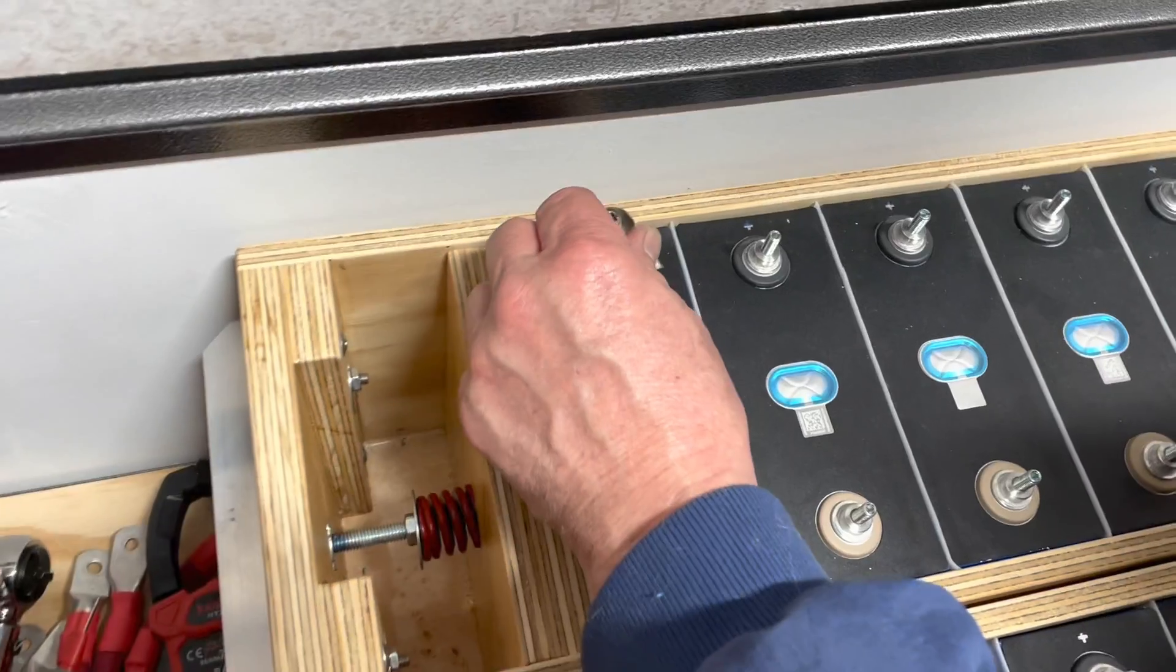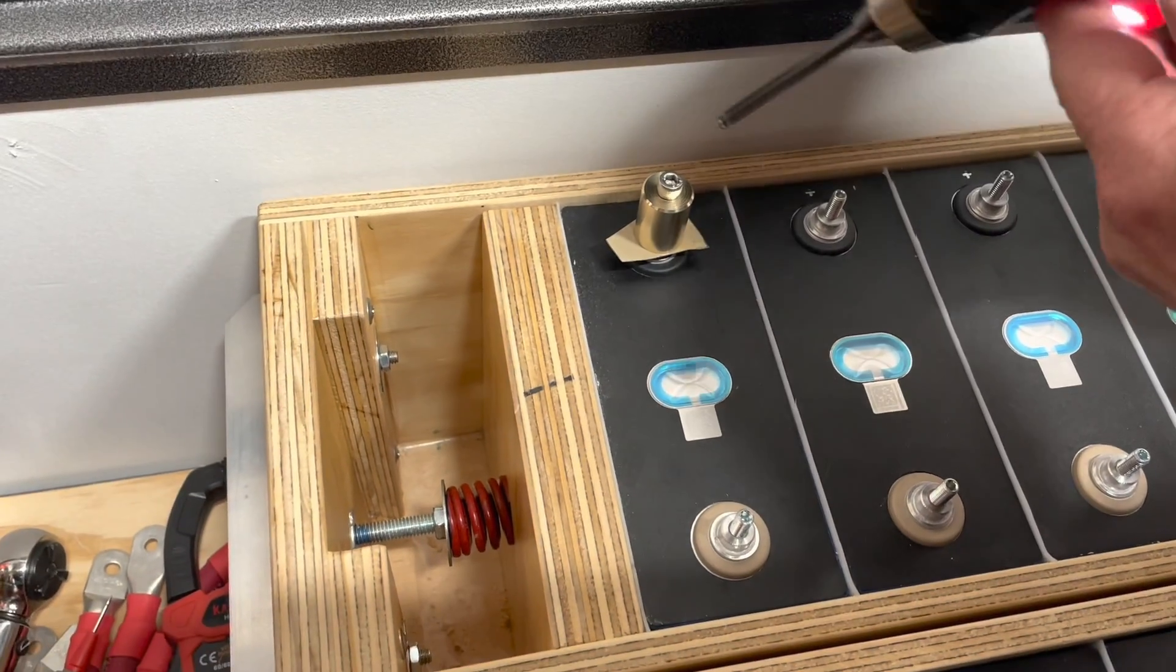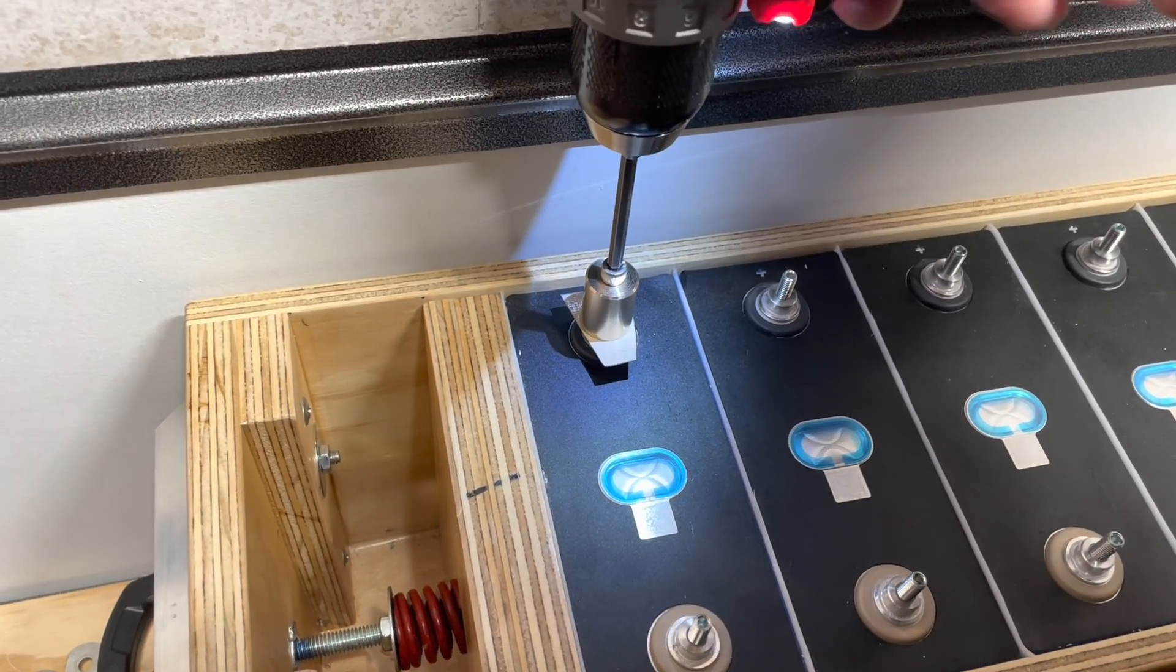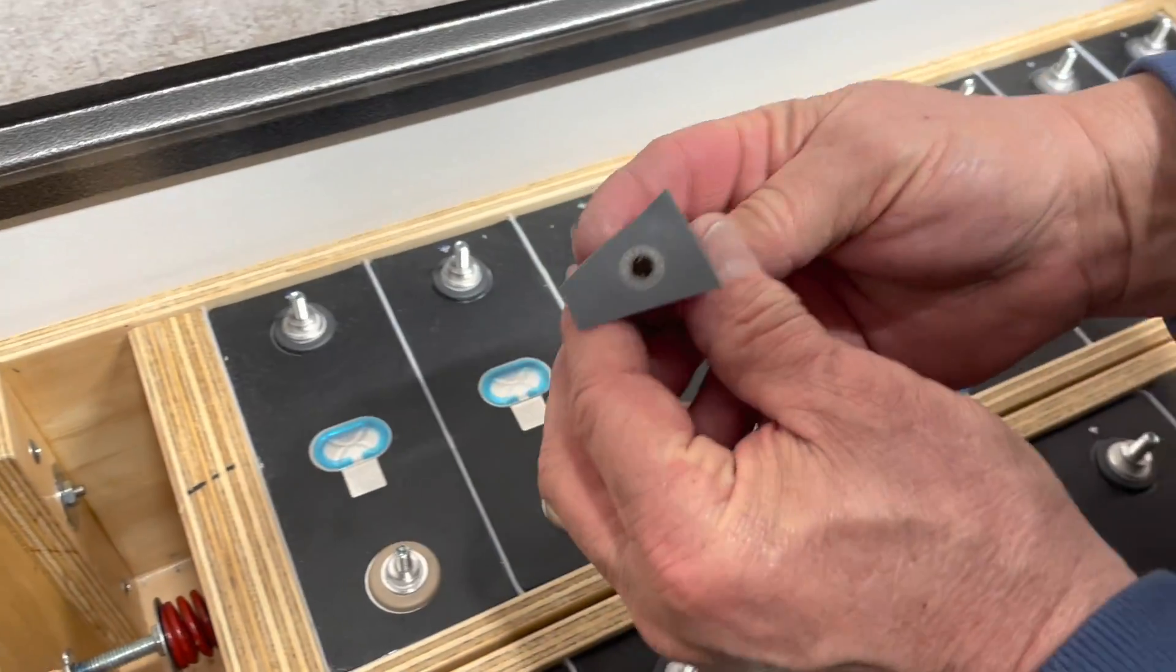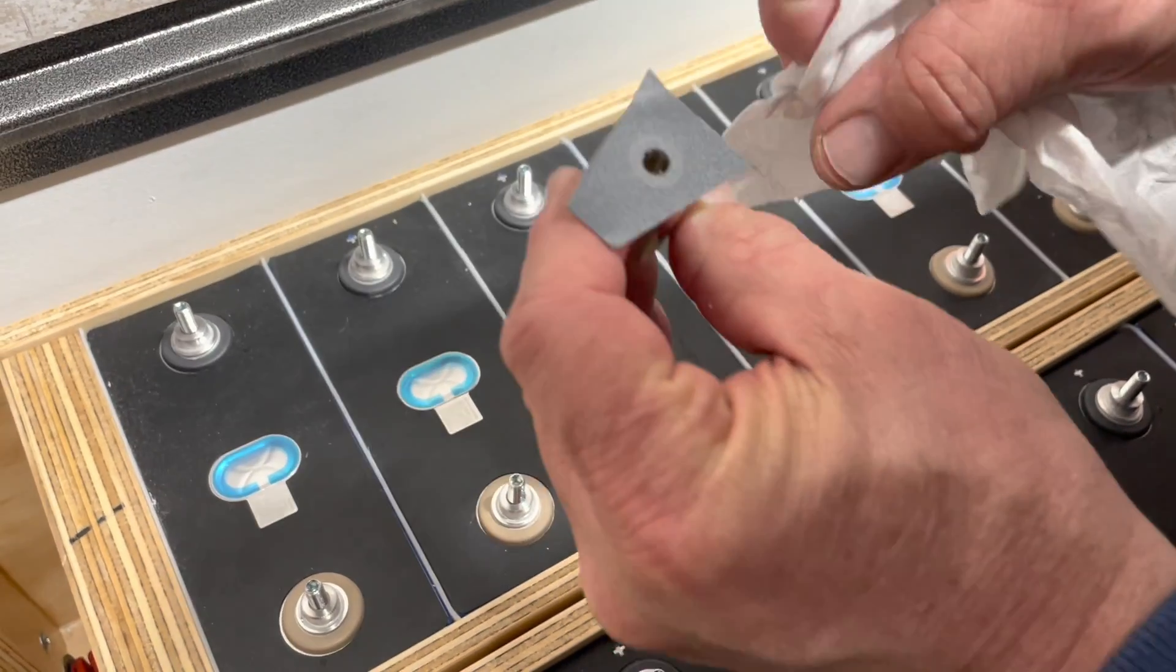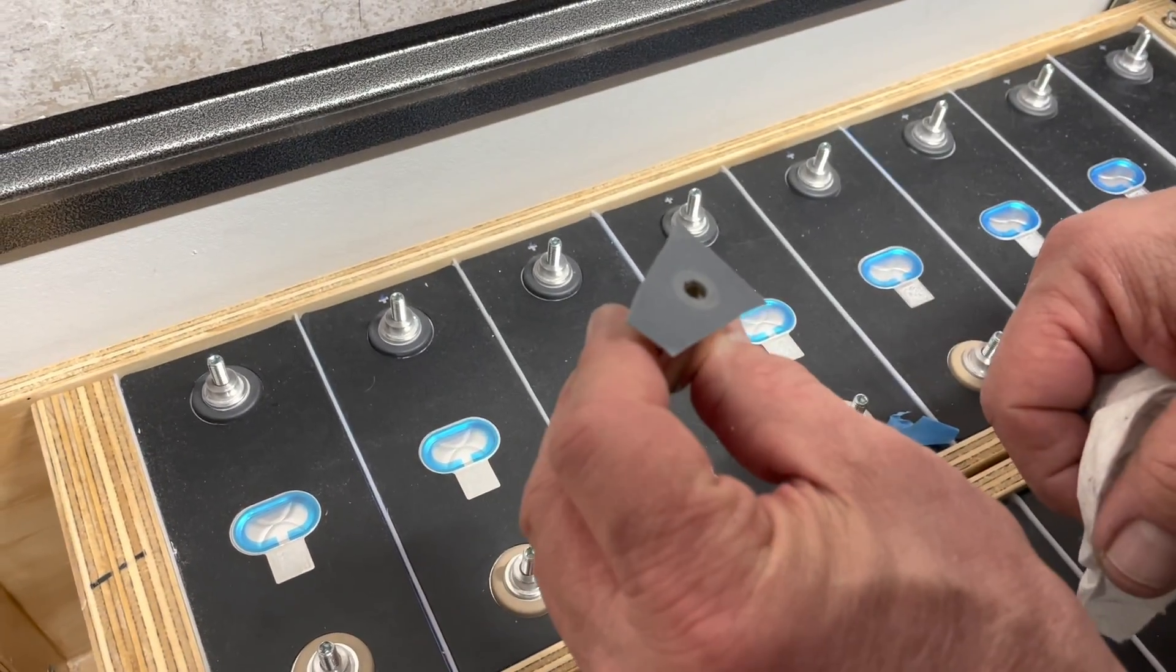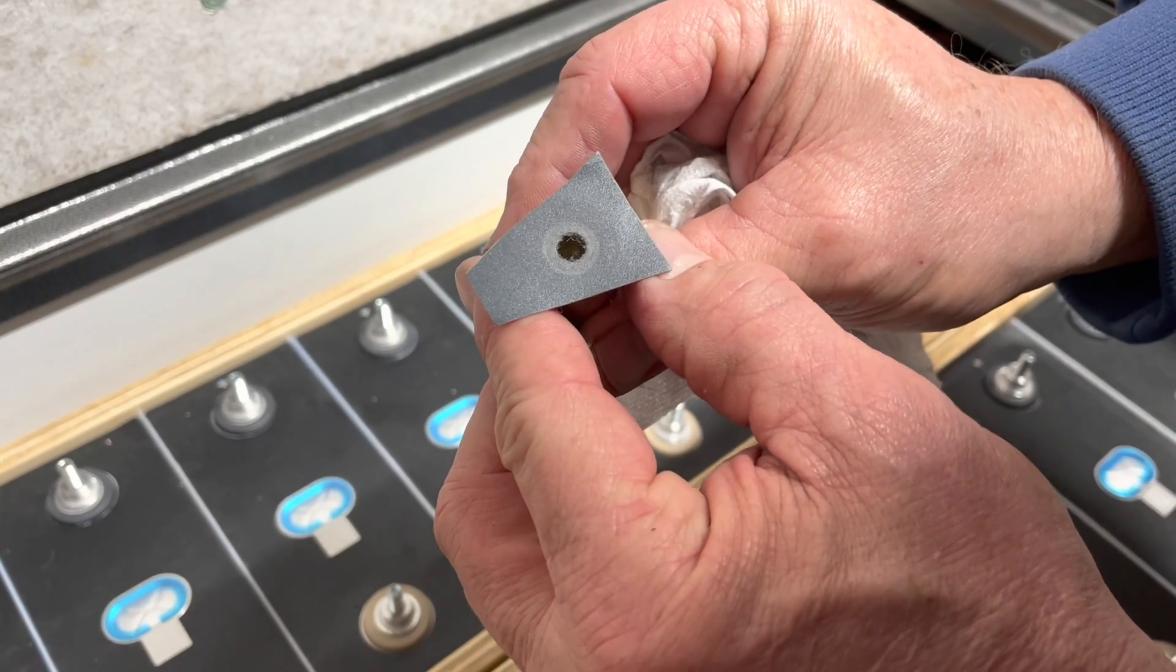One of the best ways to do this I have found by experience is to run it forward and backwards slowly. What that does is it breaks up the compound - the abrasive releases the cuttings, the dust much easier that way. The abrasive lasts a much longer time and you get a better finish. There's no trail, no tracking, no nothing - it looks really nice.